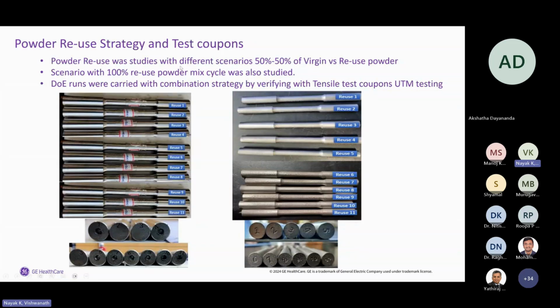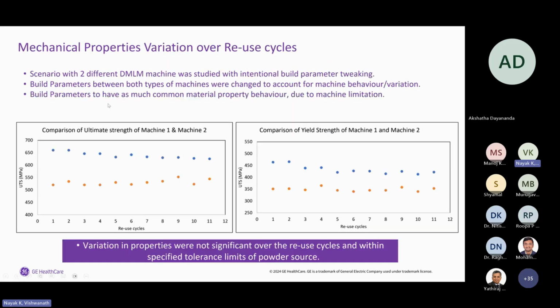If you see, there are different versions, and people use different terminologies and different methodologies, but we use a scenario where we mix 50% virgin powder with 50% reuse powder. We combine that for every reuse, and the scenario of 100% reuse was also studied, to see how it does. DOE runs were carried out, and we looked at how the tensile test coupons behave. So for different reuse cycles, we test, we mark, and we perform the analysis and testing. And this is one example.